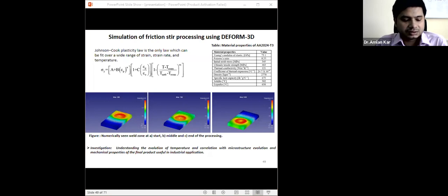And we have also modeled the process, and we have seen the temperature evolution in this process is close to 410 or 450 degrees centigrade. And one of the important factors we have seen is that the temperature below the tool shoulder does not vary much. So during the process, from the retreating side to the advancing side, or the advancing side to the retreating side, or in the three-dimensional nature, we can understand that the temperature variation is not substantial in this process. So whatever mechanism is taking place on the top of the weld should also be prevalent at the bottom of the weld as well.